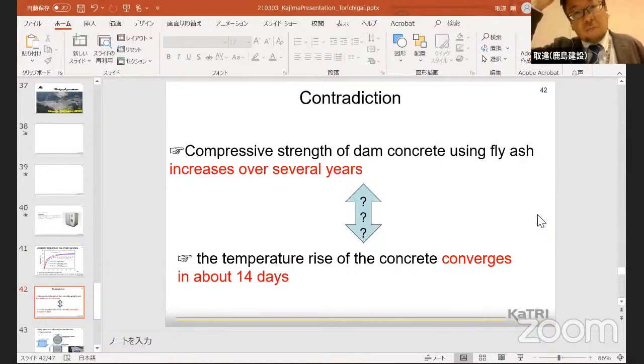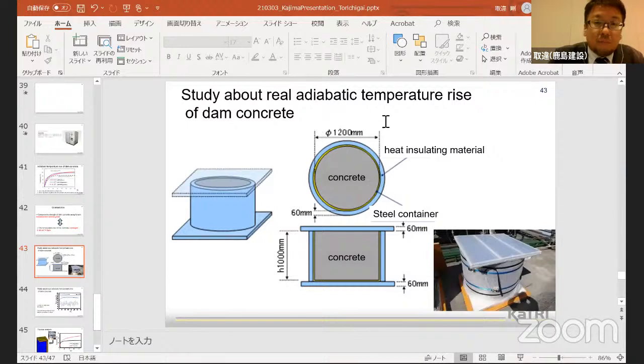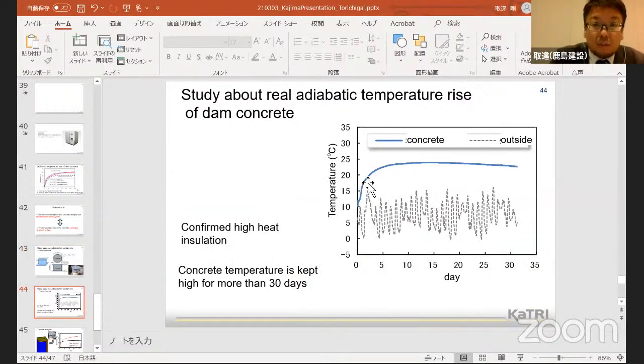I think I find a contradiction. As I explained before, the compressive strength of dam concrete using fly ash increases over several years, but the temperature rise of the concrete converges in about 14 days. That's a contradiction. So we tried to measure the real adiabatic temperature rise of dam concrete using this equipment, where heat insulating material covers the concrete and we measure the heat. That's the result: with heat insulation, the concrete temperature is kept high for more than 30 days.